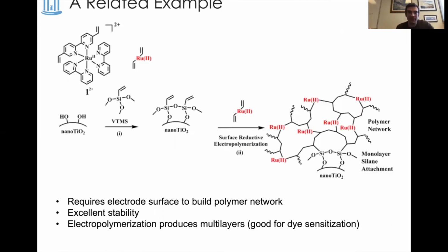So here's a related example that doesn't use azides or click chemistry, but uses the same approach of taking a silane precursor to functionalize a metal oxide surface, in this case, a mesoporous film of nanoparticles of TiO2. So this is a vinyl silane, and it forms a vinyl decorated surface. And then this was subjected to a reductive electropolymerization. So a vinyl containing Rubipi unit was brought into the reaction mixture, and reductively you form a carbon-centered radical on these olefins that kicks off a polymerization event, and you get a network of ruthenium complexes anchored to the surface by these silicon oxygen linkages.